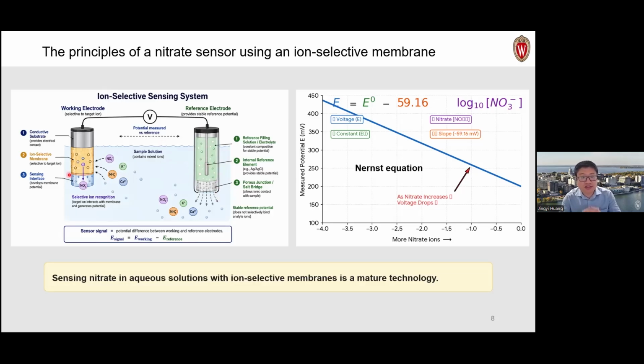So if we place this sensor in the soil environment where the soil has some moisture in it, the ions will move freely in both electrodes. However, on the working electrode, only the nitrate ions will accumulate at the electrode side, because we know that the nitrate ion has a negative charge. So the more nitrate ions you have in the soil, the more ion accumulation you're going to have at the working electrode, the more negative charge you're going to have.